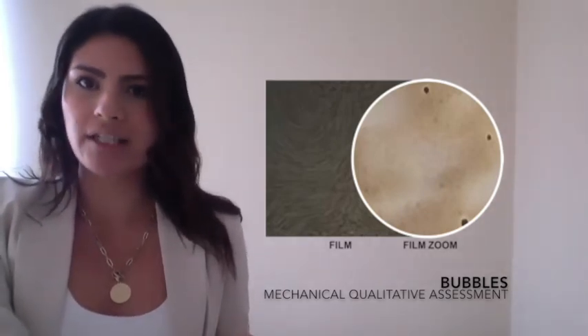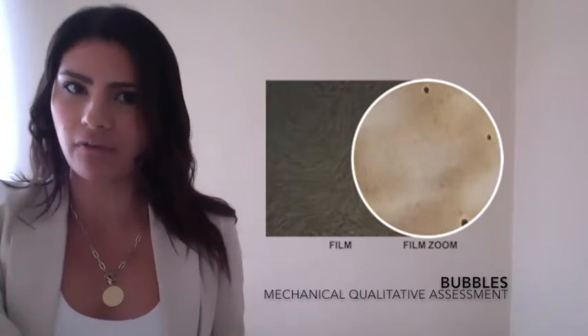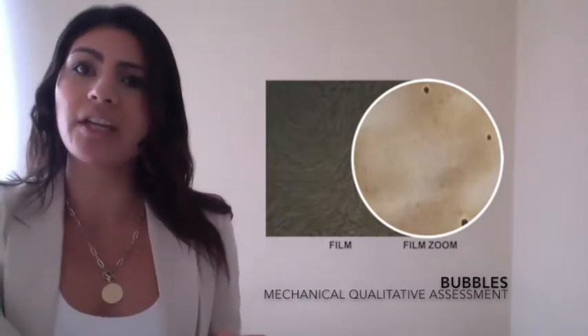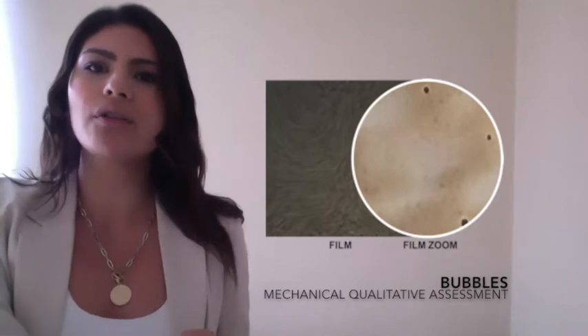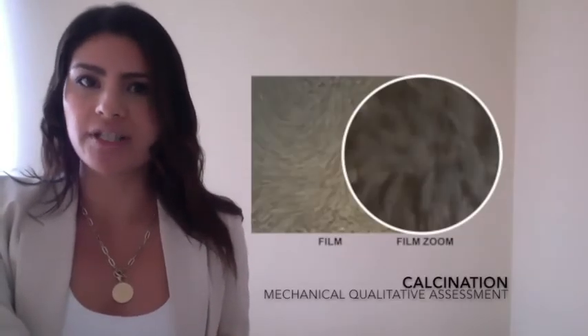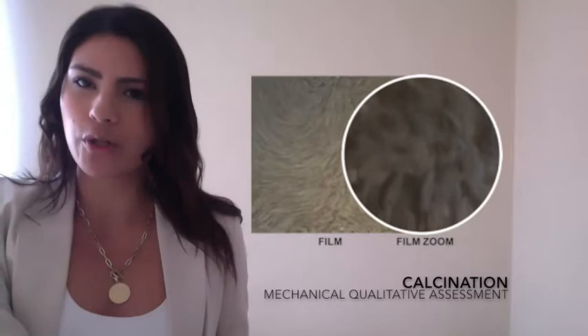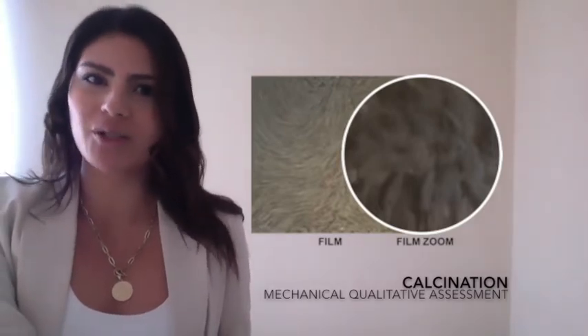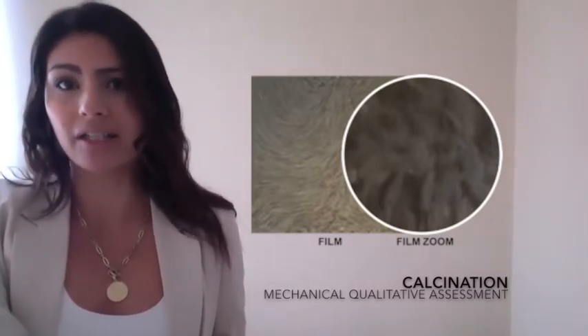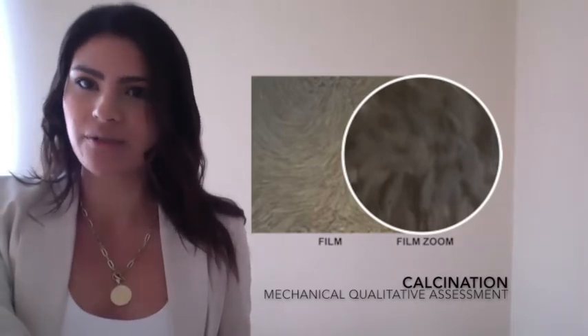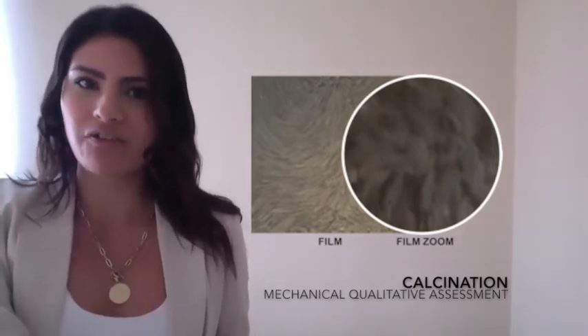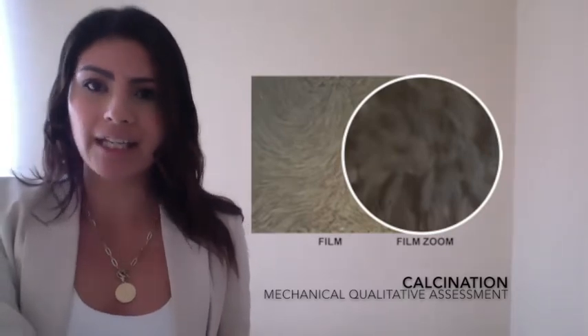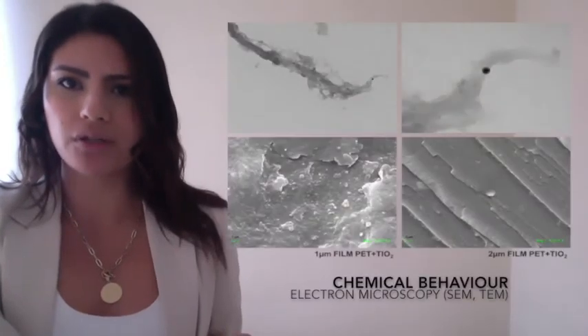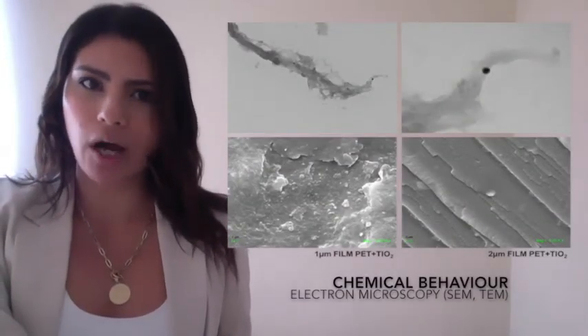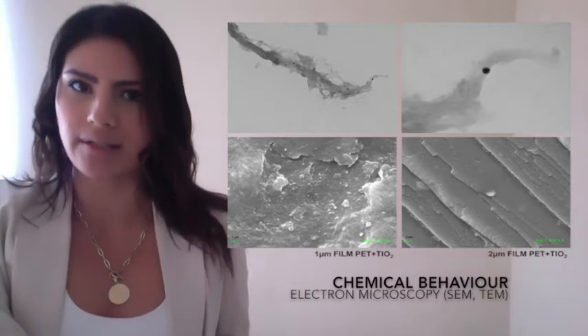The distribution of pelletized master batch on the pressing plates is another variable that affects the behavior of the film. The pressed film reveals the presence of surface bubbles as a result of uneven distribution of pellets on the pressing plates. Differences in film coloration are observed according to thermal treatment of the material during pressing. Temperatures higher than 260 Celsius degrees result in calcination at the edge of the film and directly affect the mechanical properties of the material. Following incorporation of titanium dioxide nanoparticles, the chemical behavior of the mixture was analyzed.